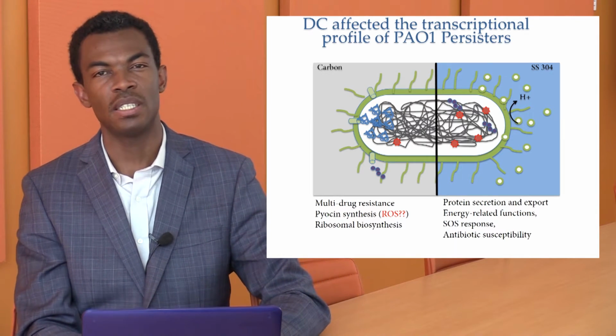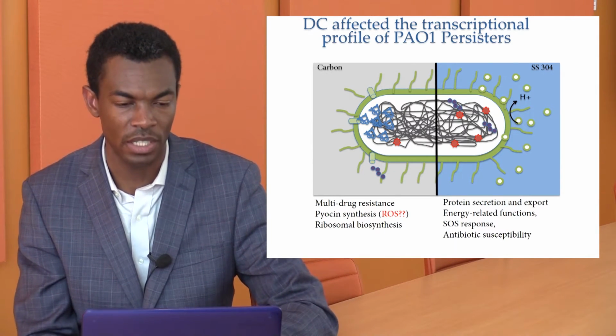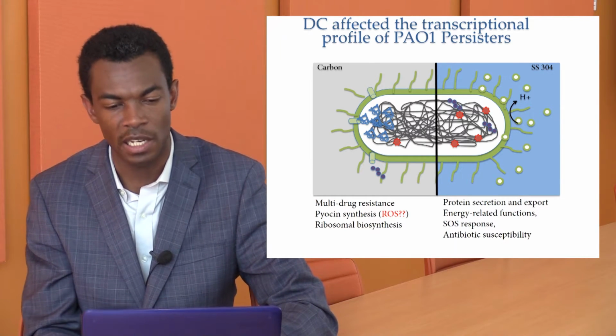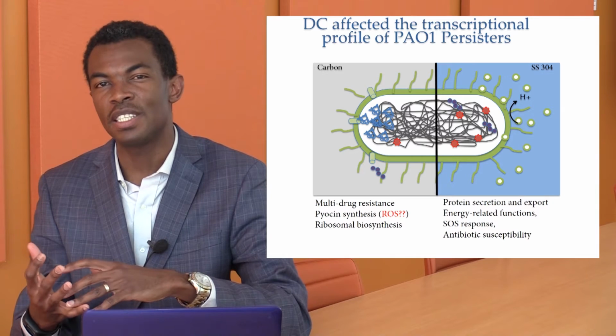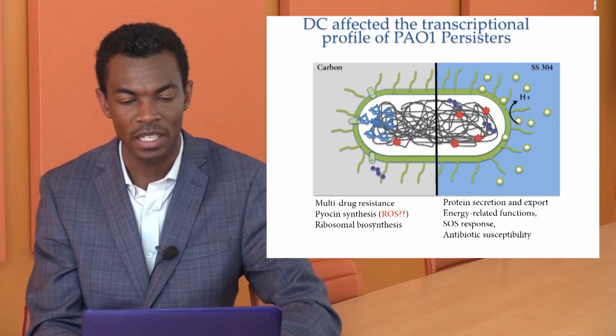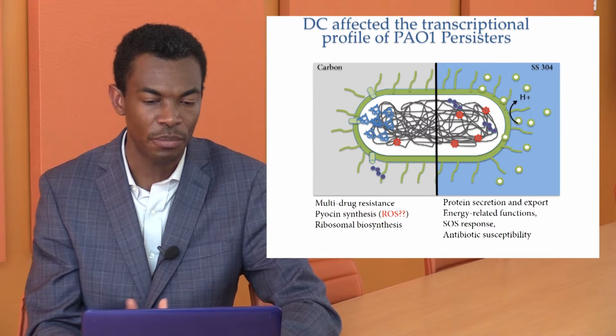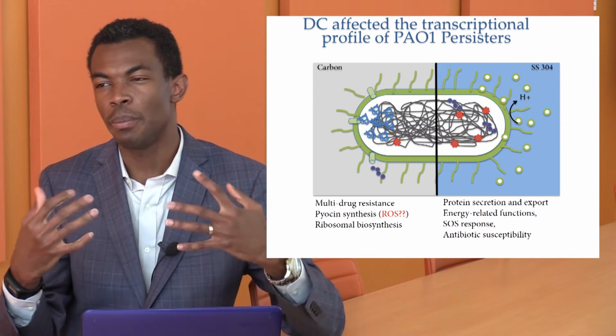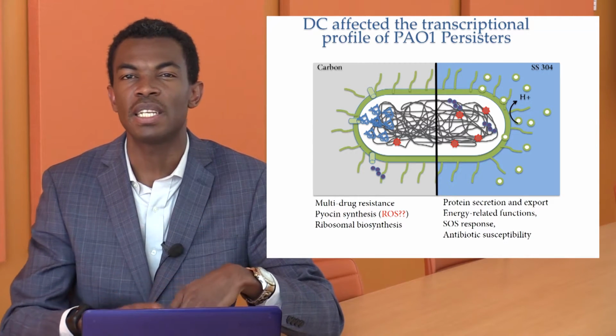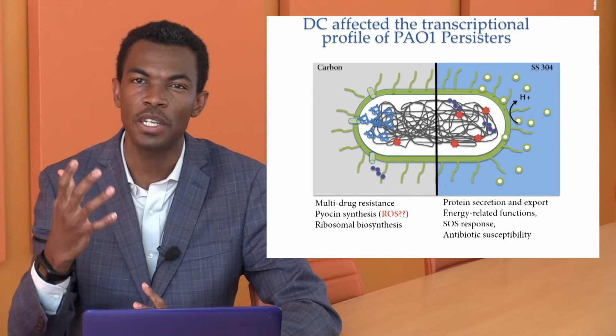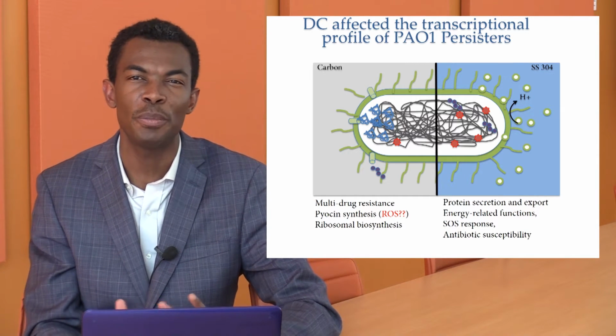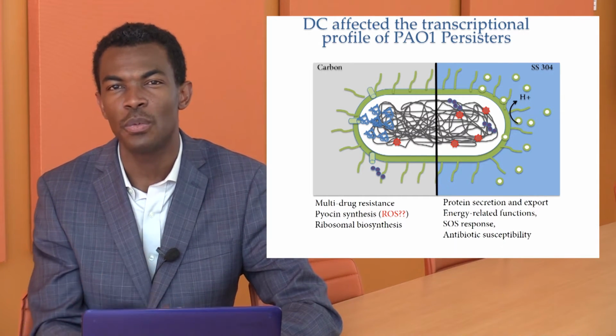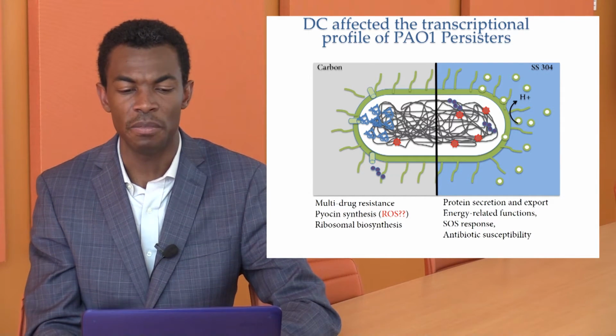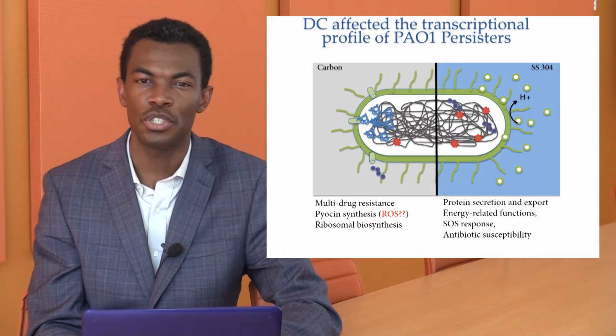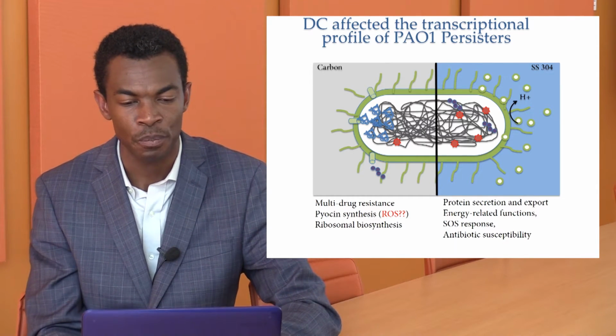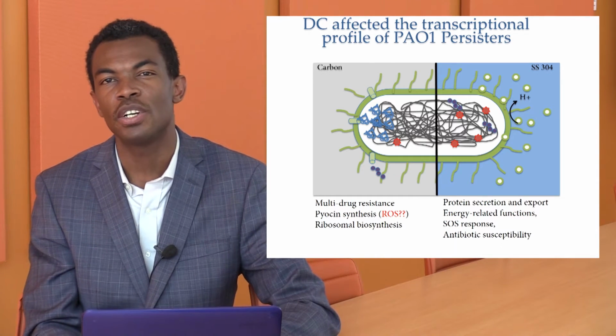Also, the ribosomal biosynthesis was expressed because the cells, as we mentioned in the carbon treatment, produce so much material inside. But on the other hand, the cells treated with stainless steel electrode start producing a lot of things. We saw the expression of proteins, secretion and export, meaning that the cells start producing a lot of proteins that can even be exported outside of the cells. And this makes us think already of the OMVs, the outer membrane vesicles, that we were able to identify when the cells were treated with stainless steel. And the cells also upregulate functions that involve energy, by trying to pump some material outside.